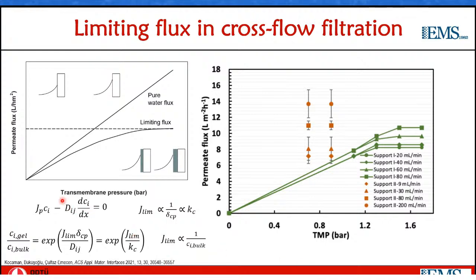nanocrystals. So what we know from cross-flow filtration of colloids is that when you increase the transmembrane pressure, the permeate flux does not increase linearly as it would in the case of permeating a pure solvent, but rather it increases linearly for a while, and then it levels off at what is called the limiting flux. So what happens is that at low transmembrane pressures, for the rejected species, the concentration increases at the membrane wall, which is why the permeance is lower than the pure water permeance.